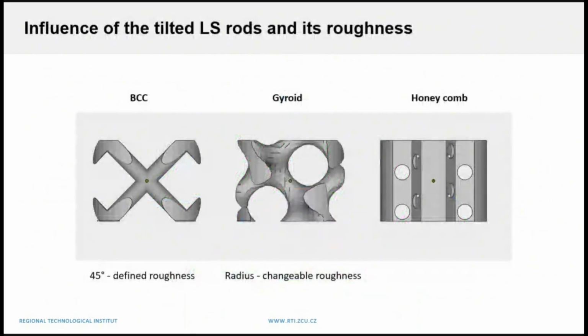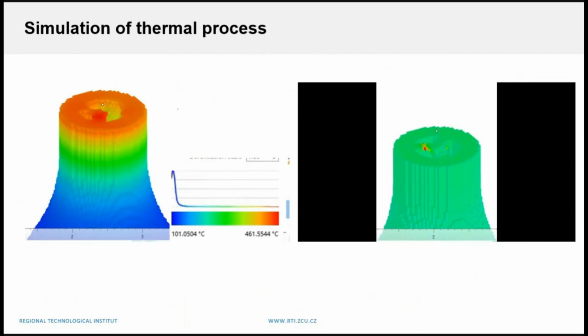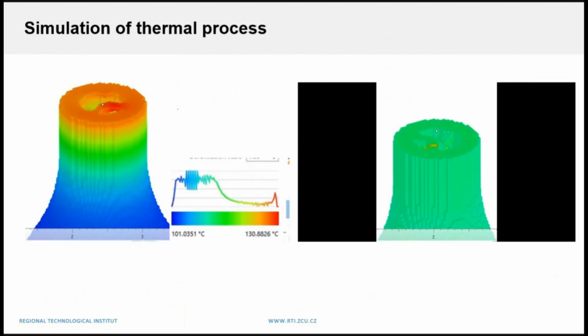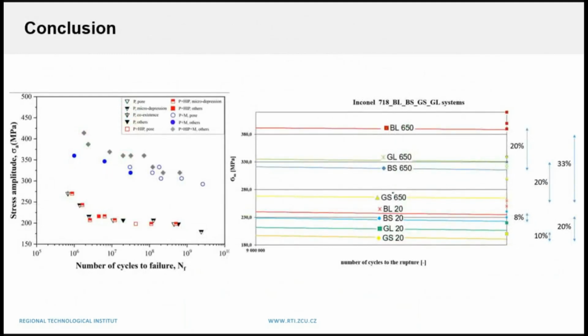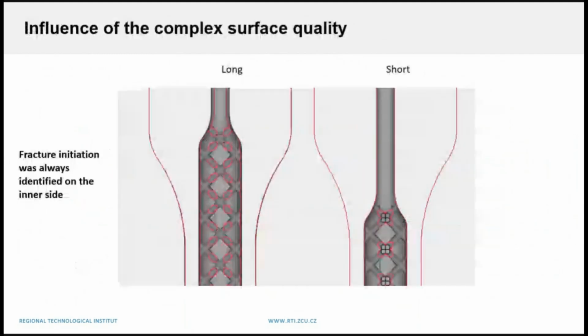The next point is that in this case, on the bottom, we can say it's a 45 degree. It's a constant roughness of about 15. But in the case of gyroid, the roughness is changeable on the basis of the radius. Now, here you could see the simulation, and in the critical area of the connection of the rods together, the simulation really indicated the overheating area. So this is why there are big differences.